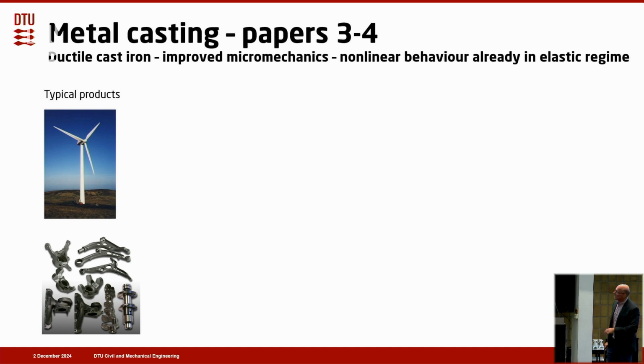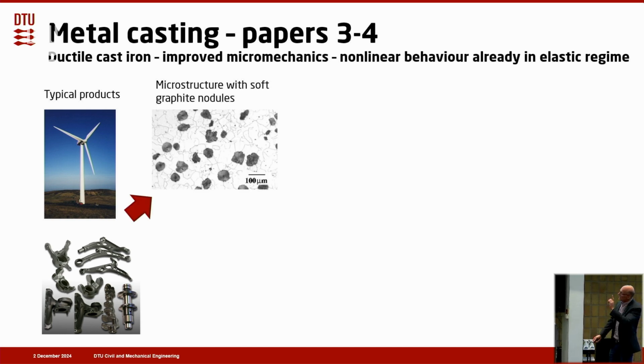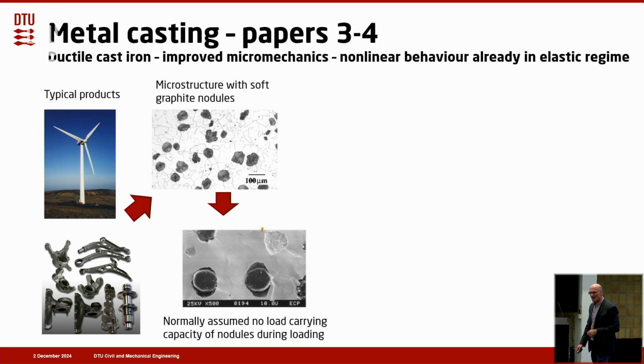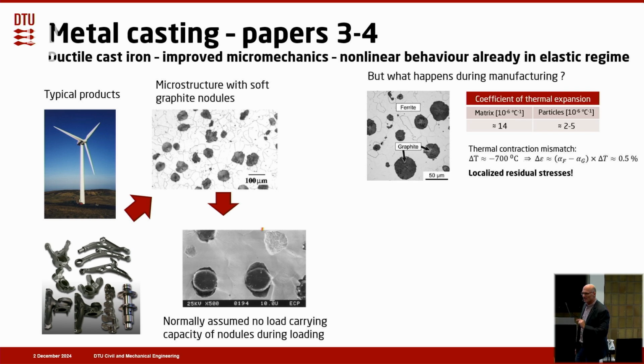The next two papers were about ductile cast iron, improved micromechanical models that could somehow address the nonlinear behavior already in the elastic regime. So here you see some examples of ductile cast iron. Now, the microstructure in ductile cast iron contains soft graphite nodules, and these are for castability. But typically, you don't assume that they can carry any load because they're soft. So therefore, you just assume that there are holes when you dimension the thing. But the point is, what happens during manufacturing? Because you have different thermal expansion coefficients of the nodules and the surrounding matrix, which means that you get localized residual stresses. And this is important for how it carries load afterwards.